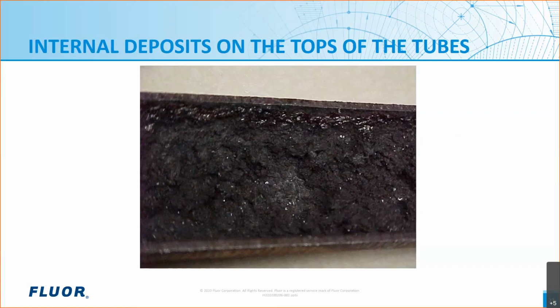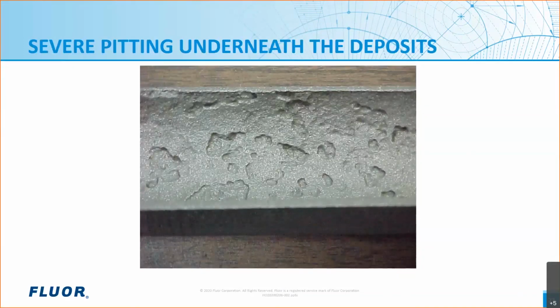And you can see it had a heavy deposit, and the headers of this air cooler also had heavy deposits. In a lot of areas, the deposits were very white, but you can see this looks black because there's also hydrocarbon on the outer surface of the deposits. So this is what it looked like after those deposits were removed. This is the classic appearance of ammonium chloride corrosion. Because it's a corrosion under wet deposits, it's often very pitted looking. And you can see some of these pits look like they're just about through wall, and this pitting is what led to all those tube leaks we saw in that first tube layout drawing.